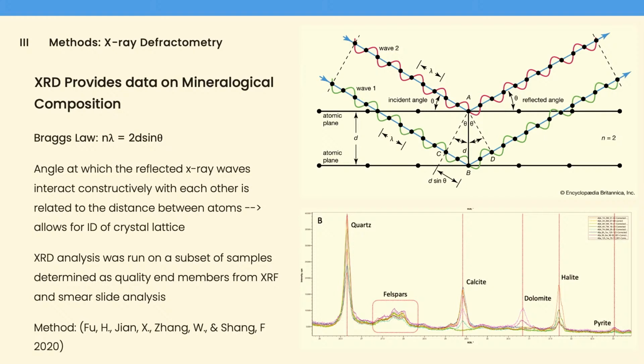And so we see a peak associated with a particular crystal or a particular mineral. So here, most notably, you can see the quartz peak, which is the peak that I used to align my data, because we had a lot of quartz in all of our samples, so it was really easy to use quartz to align everything. Then we have feldspars. There's a lot of substitution of ions in feldspars, so that's a little bit wider in terms of peak. Importantly for me, we have the calcite and dolomite peaks, halite, which is just table salt, and then pyrite at the far end.